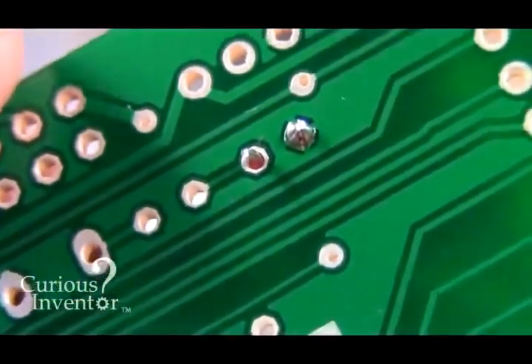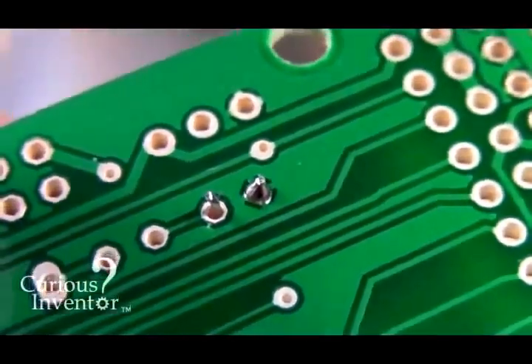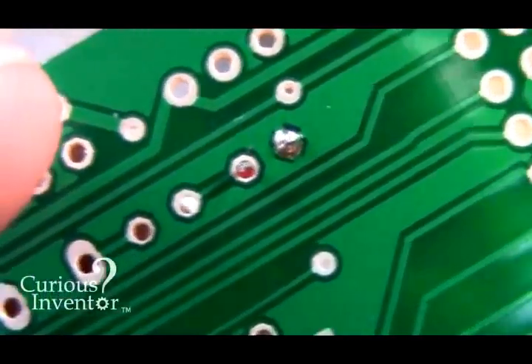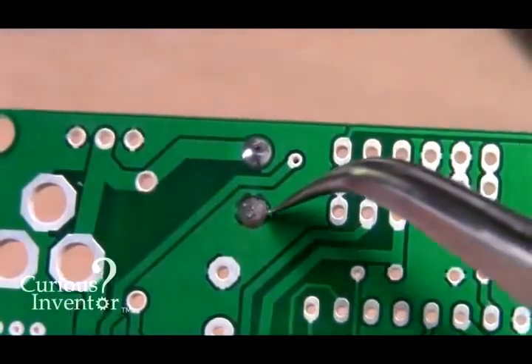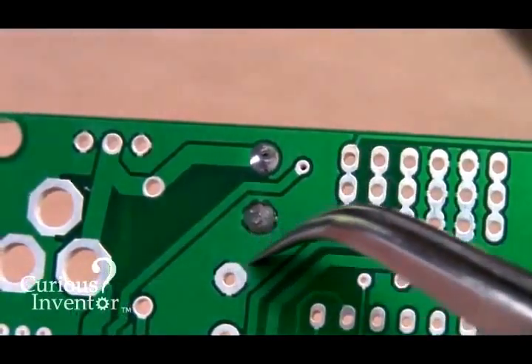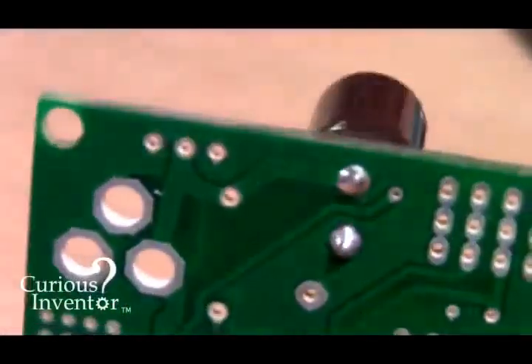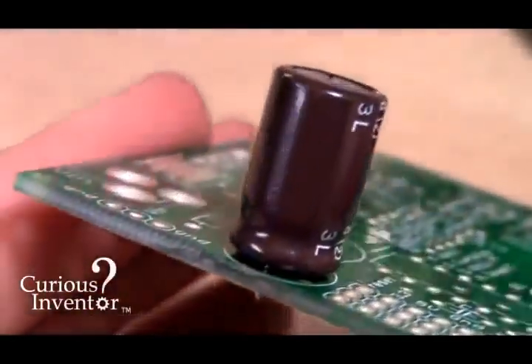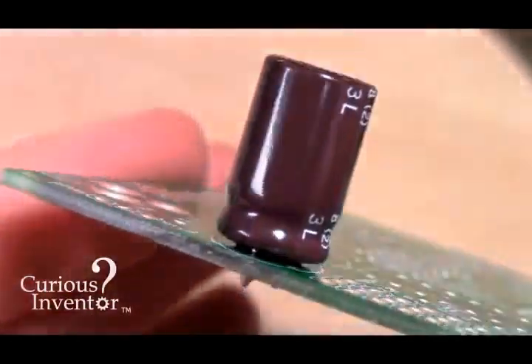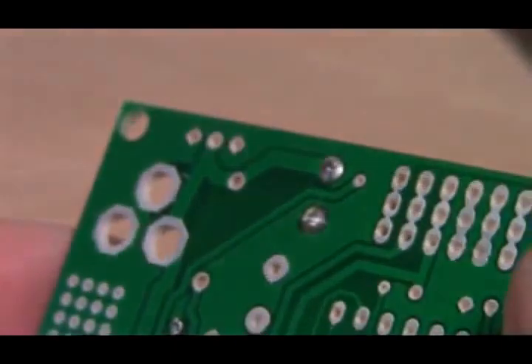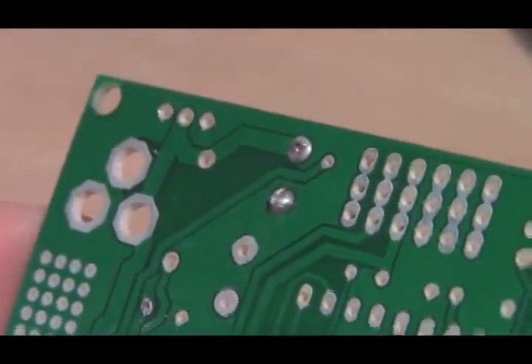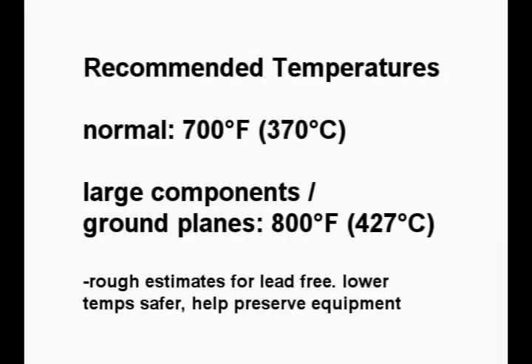Some joints are much more difficult than others to desolder. For instance, when you have a small hole with a very small clearance. Also, when a hole is attached to a ground plane, it can be difficult to heat up the joint sufficiently. A large component like this capacitor also adds to the heating requirements. In this case, if you only have wick or solder sucker, your best bet is to use a higher temperature setting. Unfortunately, the higher the temperature and the longer duration of desoldering operation, the greater risk of damage.